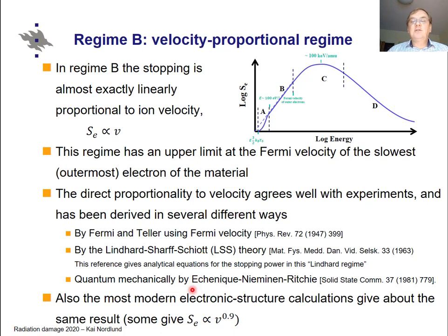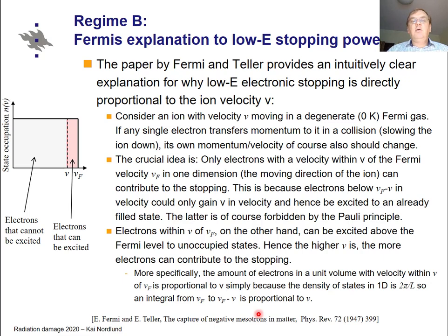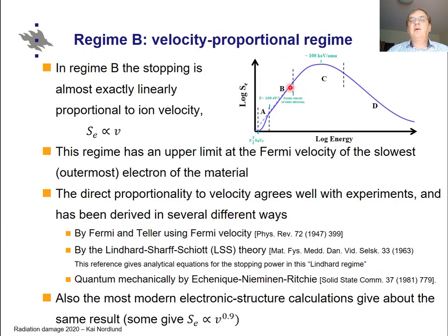More modern theories have derived this quantum mechanically. The best known is the Echenique-Nieminen-Ritchie theory, developed around 1980. After this, many other theories which are extensions of it agree that the electronic stopping is proportional to velocity. Some of the most modern electronic structure calculations give a proportionality of velocity to the power of roughly 0.9, so it is well established that the stopping power in this regime is proportional to velocity.